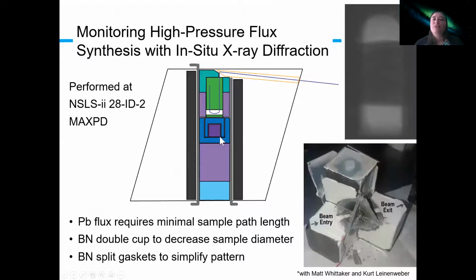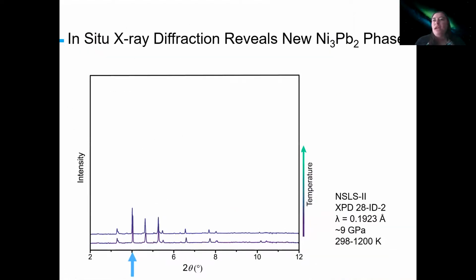And inside one of these octahedra, one of the modifications that I needed to make here was to decrease the sample size. So normally this sample space is taken up by a large, about 2.5 millimeter pellet. I needed to decrease the size of that pellet in order to get X-rays through here. But otherwise I used the standard setup available from COMPRES. And then I was able to do some in situ X-ray diffraction.